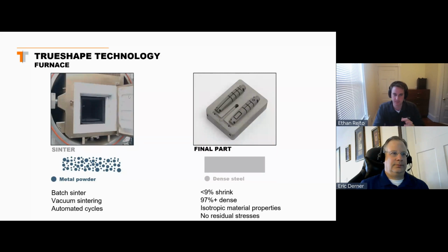Any binder in the part's going to be removed. It's going to shrink just a little bit, just about 9% here, and I'll explain how we're able to achieve such a low shrinkage. And the result is going to be a 97% dense and above tool steel component. You probably can't hear it, but these are tool steel dense components that are ready to go into molding environments, very, very demanding environments. You're also getting isotropic material properties because we're doing this uniform heating and sintering process. And you're not getting any of the residual stresses that you commonly see in a laser process because we're very, very uniformly heating and cooling our part.